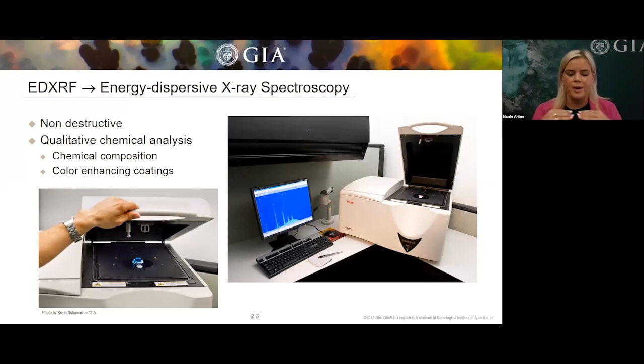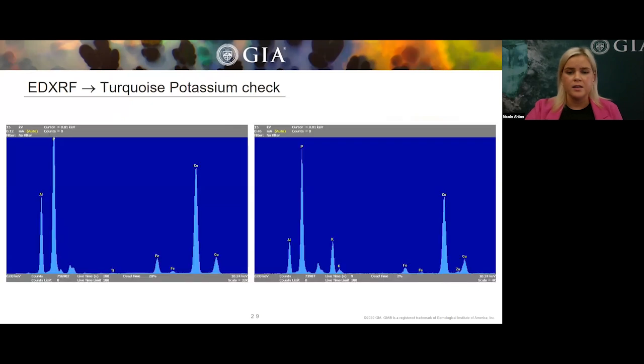And examples of when we might use this technique is checking for levels of potassium in turquoise to see if it was Zachery treated or not. We can use it for our rubies if we think that it was a manufactured product consisting of lead glass. We can again use it for tourmaline to check for that copper, the manganese, the presence of chrome. We can use it for possible tanzanite coating. So again, we're going to be looking for cobalt and titanium in this case.